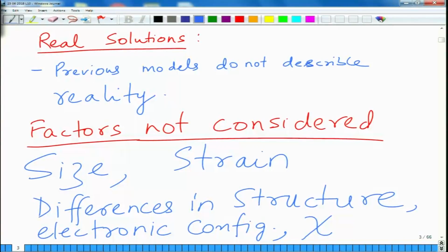So, all these differences matter. As we saw in the structure of materials module, the formation of solid solution is governed by certain rules called Hume-Rothery rules, which say that solid solution will form when the size difference is smaller than a certain number, when the valences of those two elements are ideally similar, or the electronegativities are similar and the structures are similar. So, these factors which were not considered in the first two models of ideal and regular solutions make the situation far more complicated, and as a result you do not necessarily form a substitutional solution.